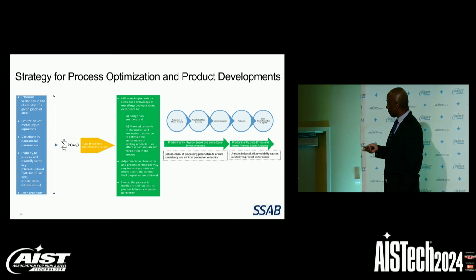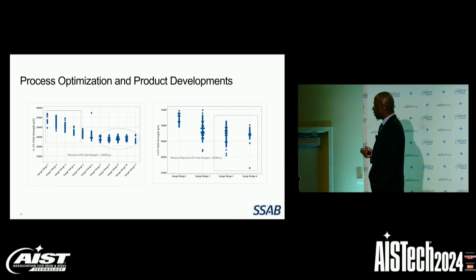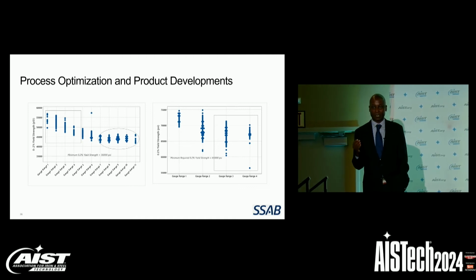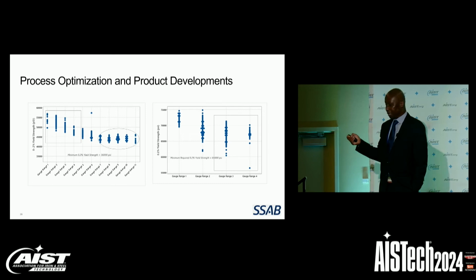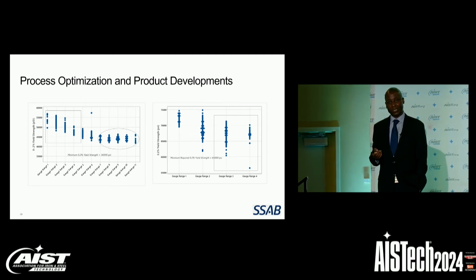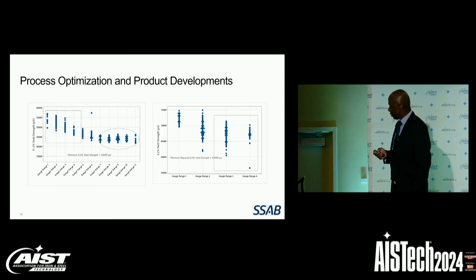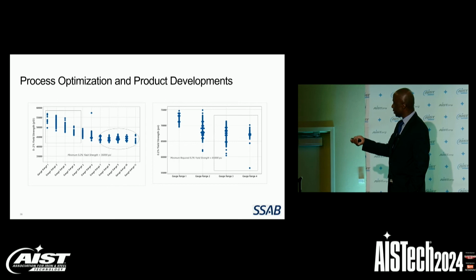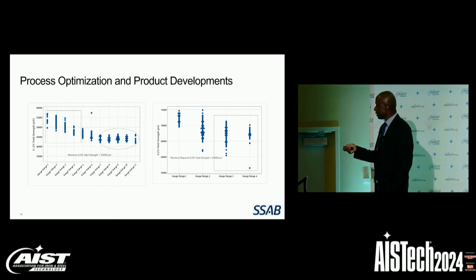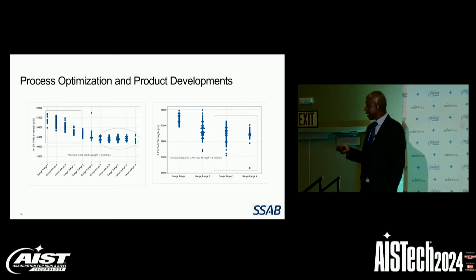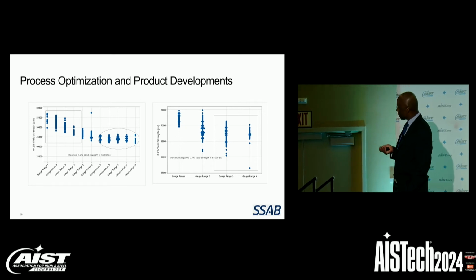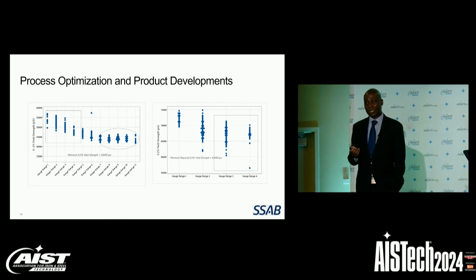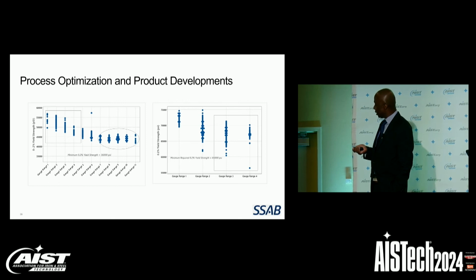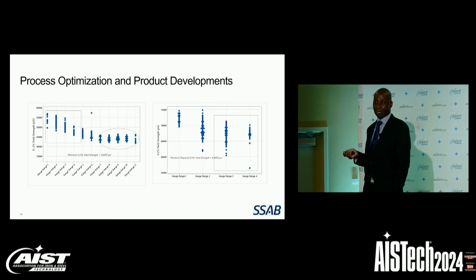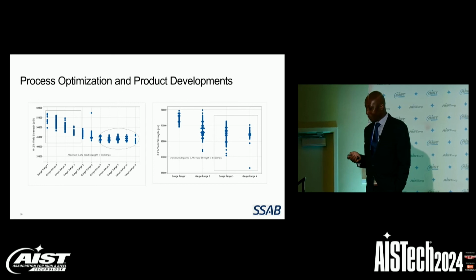The charts that I'm going to show in a second show the relationship between the yield strength and thickness of two grades of steel. On the left is a grade requiring 36,000 psi minimum yield strength. You can see that all of the products there meet this requirement. But if you look at the lighter gauges, they are about 10,000 psi higher than the heavier gauges. Now, on the right is a grade of steel requiring a yield strength minimum of about 65,000 psi. You can see that when you go to heavier gauges, you begin to see products with yield strength that is below the required minimum of 65,000 psi.